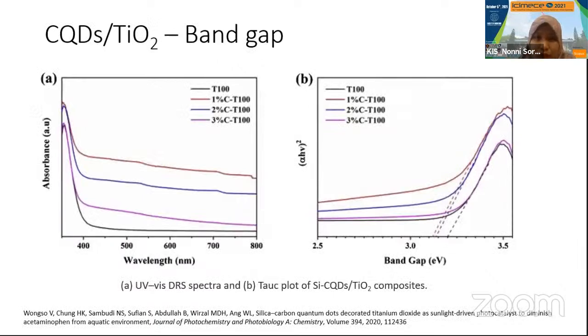So the incorporation of the carbon quantum dot in the titania can actually reduce the band gap further. This indicates a good property, the decreasing of the band gap, meaning that we can go to the visible light area sensitivity, which means that the composite material is now more able to harvest the visible light from the sun.